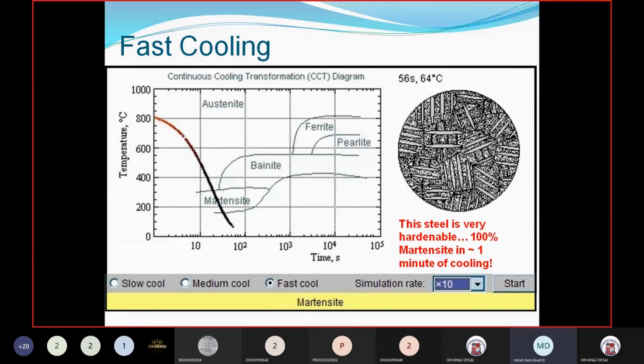So just by doing a different way of cooling in the same material, we are getting much more hardness. So if my application requires only hardness and good strength, I don't have to do any alloy addition. Just make the plain carbon steel and do the hardening treatment, because this martensitic phase itself is very hard and brittle, and almost double hardness you are getting.